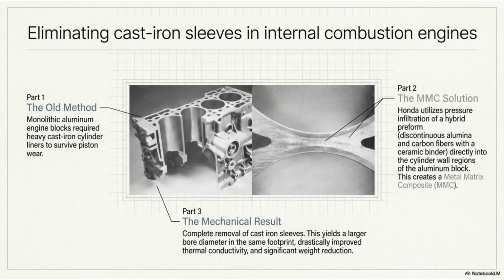This slide focuses on eliminating cast iron sleeves in internal combustion engines. Honda's MMC solution uses pressure infiltration of a hybrid preform into the aluminum block. This creates a metal matrix composite, removing heavy cast iron and yielding larger bore diameters, improved thermal conductivity, and significant weight reduction.